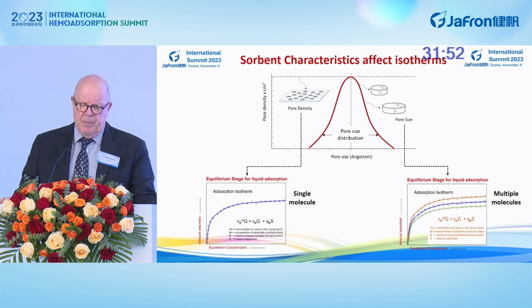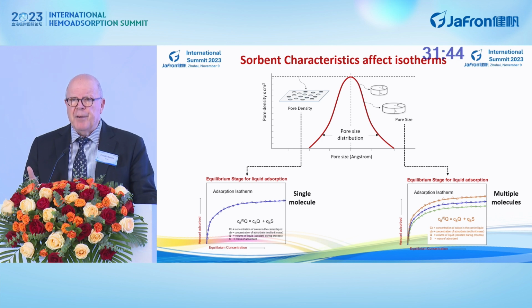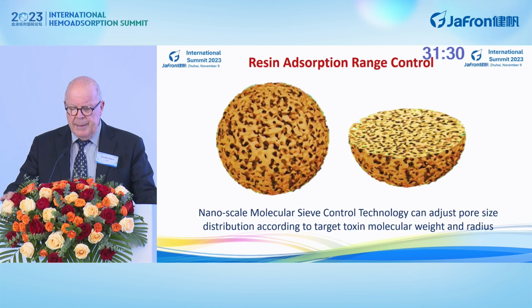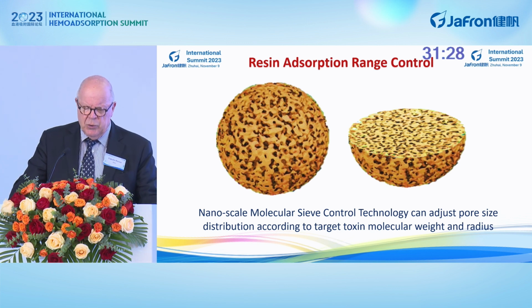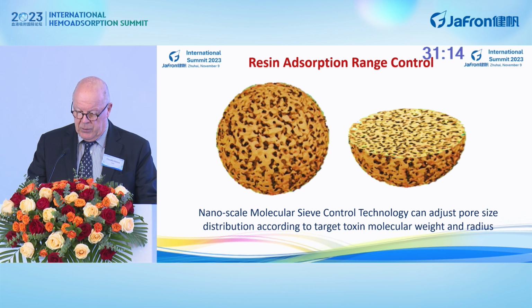So these isotherms, as you can see here, can be influenced by the pore density. A specific molecule will have a different isotherm depending on the porosity, and also the pore size distribution will affect the different isotherms for different solutes. Now, it seems very interesting today that Jaffron has a proprietary technology to make a nanoscale molecular sieve control, adjusting the pore size distribution according to the target molecular weight and radius of the substances.